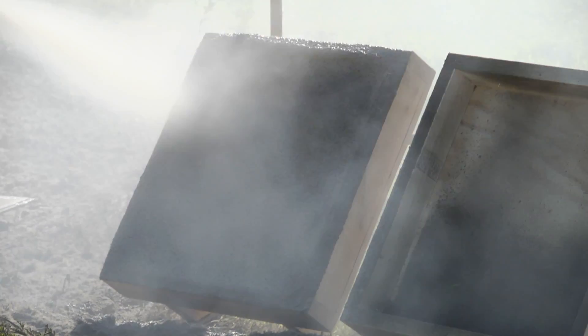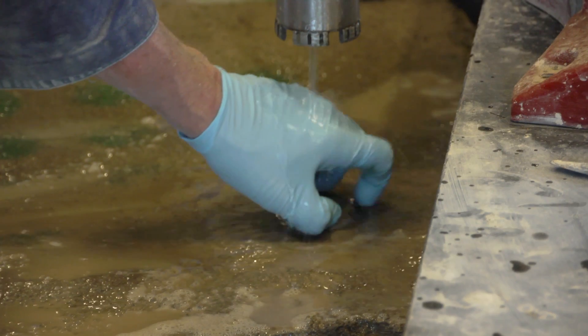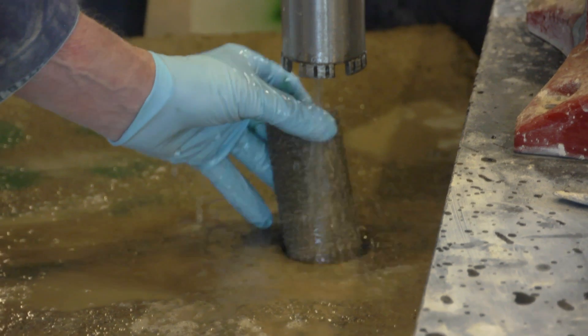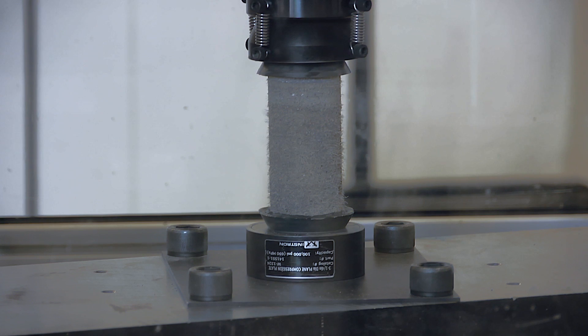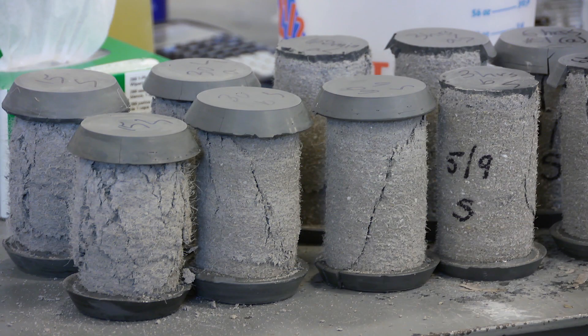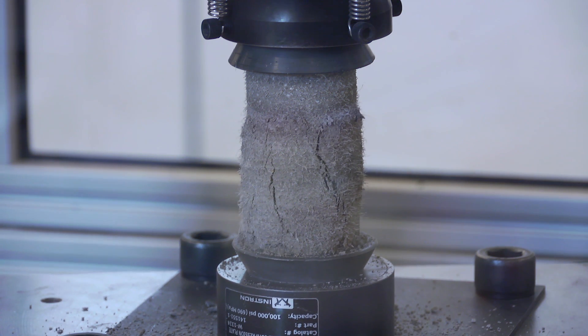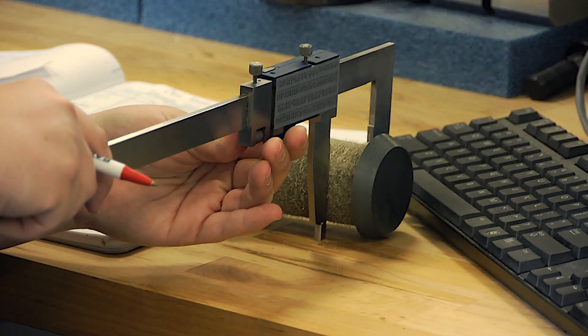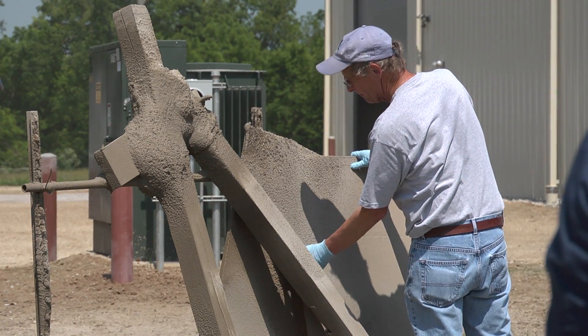The goal was fast-setting strength, but also continuity — they didn't want catastrophic failure. In the case of first responders entering a building, you want structural integrity beyond load capacity, and the fibers give you that. Fibers create a dense network so that instead of one main break, cracks disperse throughout the concrete. For high-strength concrete, you're looking at maybe 400 to 700 PSI in flexural strength testing, while the final product from this project achieved 1,200 PSI — tripling the capacity of its flexural strength.